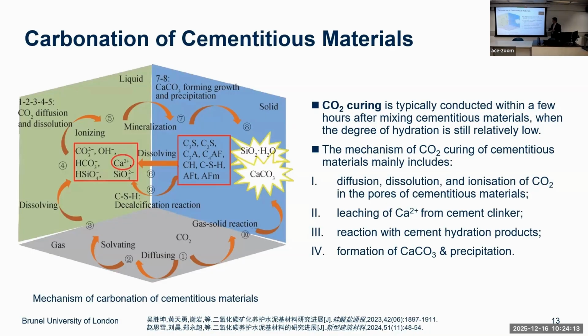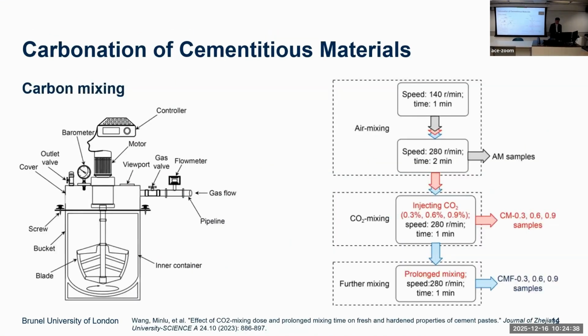We have the problem that carbonation could occur in a surface layer, then it becomes very dense, which prevents the diffusion of carbon dioxide getting deeper into the body of the concrete block, and prevents further carbonation. We use a so-called carbonation rate to quantify that effect.